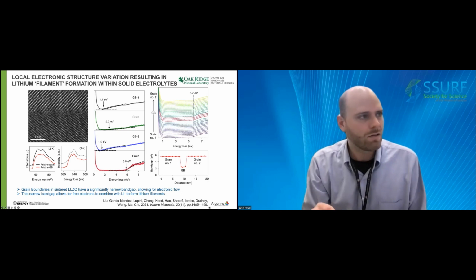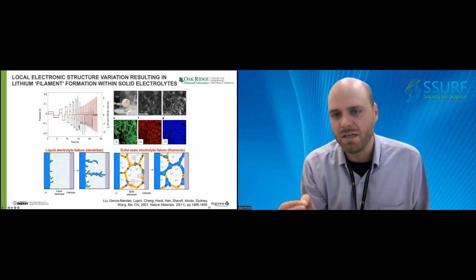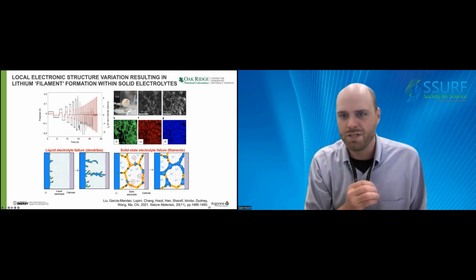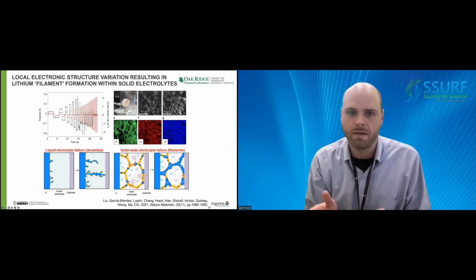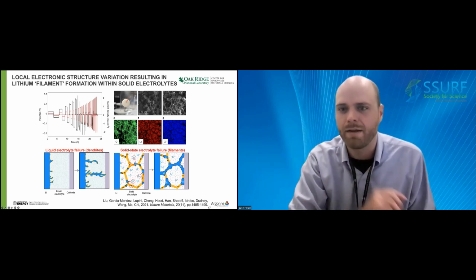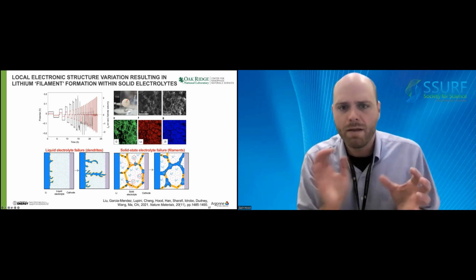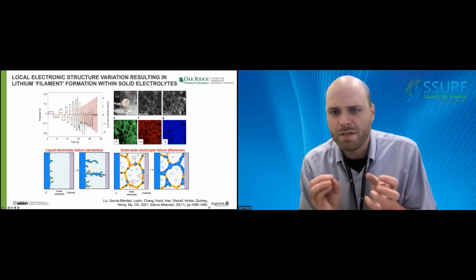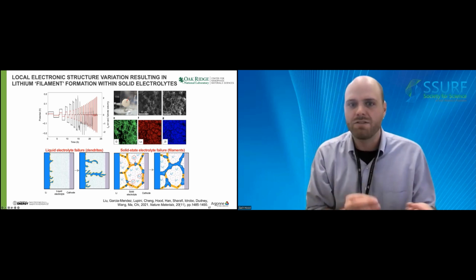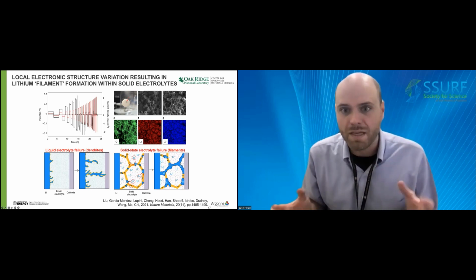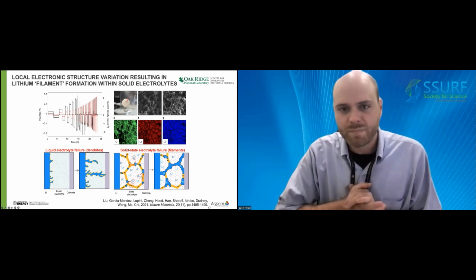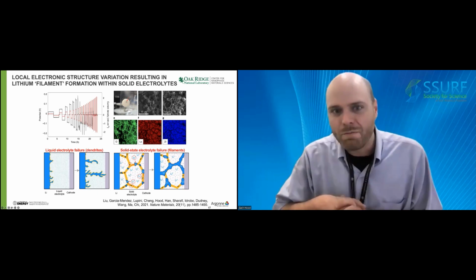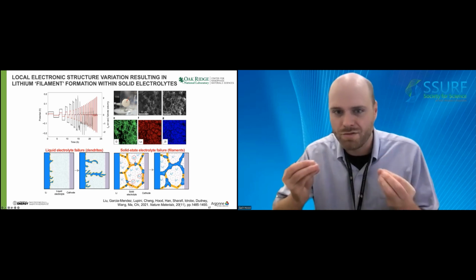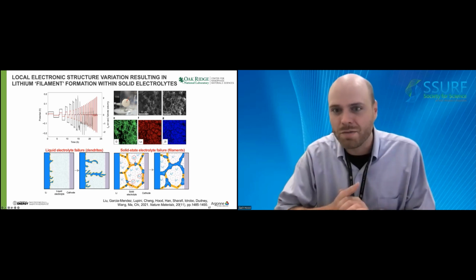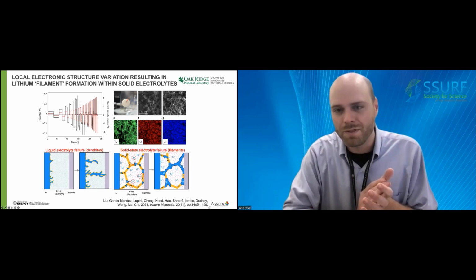So to look a little bit closer, these lithium filaments can be seen using scanning electron microscopy images after symmetric cell testing at increased current densities, which is shown on the top right-hand side of the slide. But in polycrystalline LLZO, the filamentary structures are largely confined to these grain boundaries. So the results that we collected at Oak Ridge National Lab really highlight the importance of these grain boundary chemistries and their electronic structure. It also paves the way to some new research that really guides what we're doing for